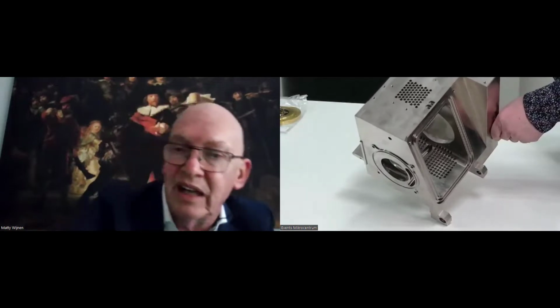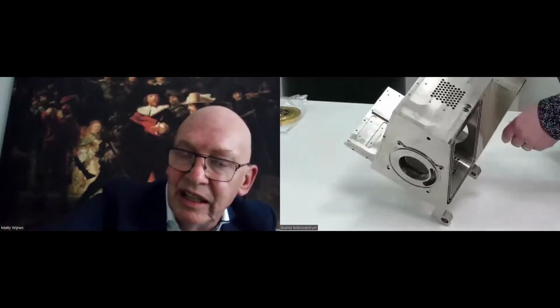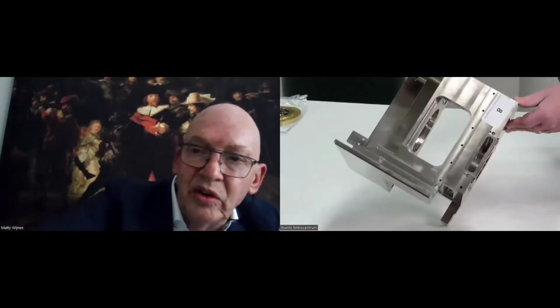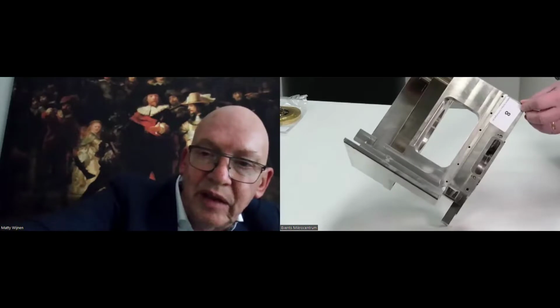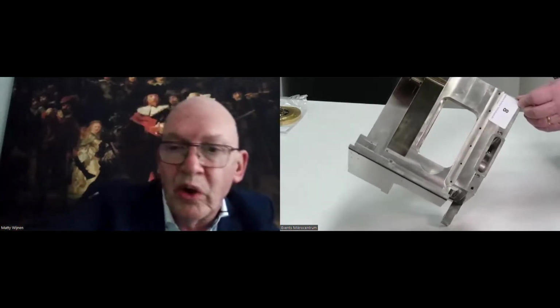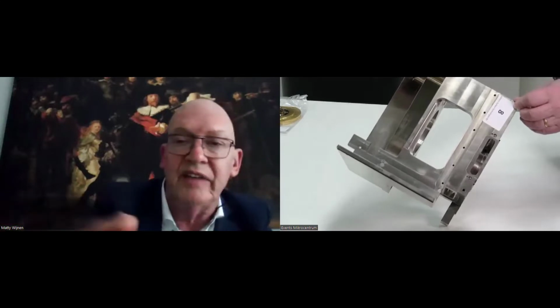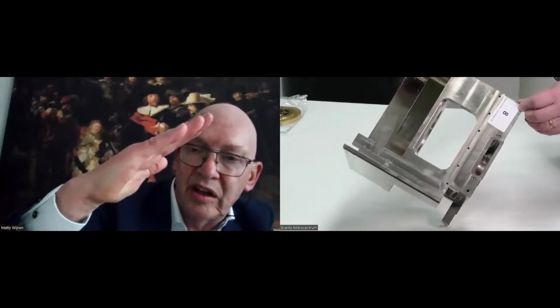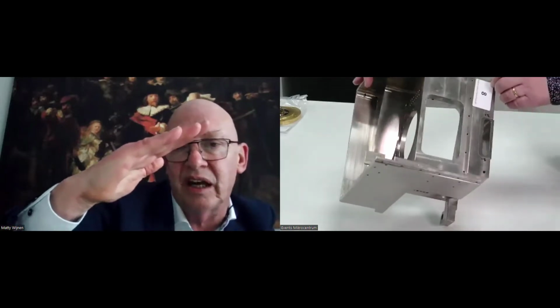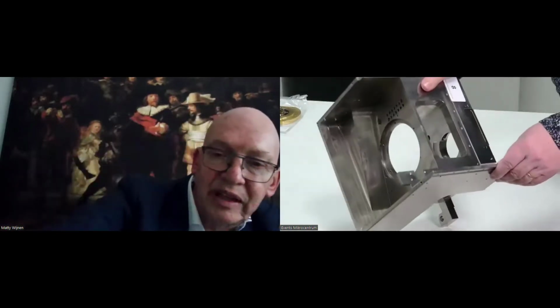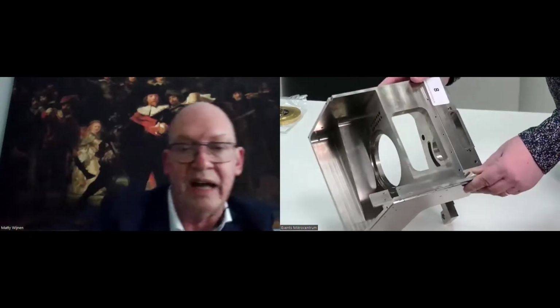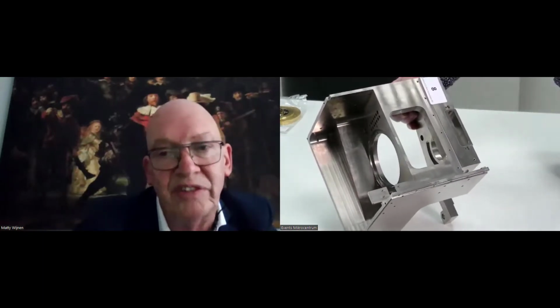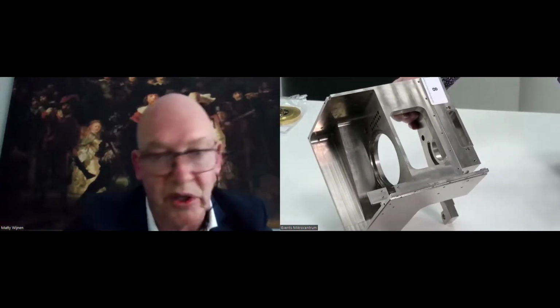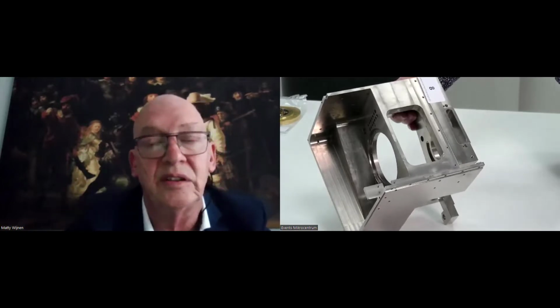Another risk on this part is, when you turn it to the other side, yes, thank you, when you hang this part upside down. What you have here in the edges is that if your part has an angle of, say, 15 or 20 degrees, you will have air bubbles there. The air will be trapped there, and that will give you airlocks, air pockets. And these air pockets will create uncovered spots, and these uncovered spots will later create corrosion.